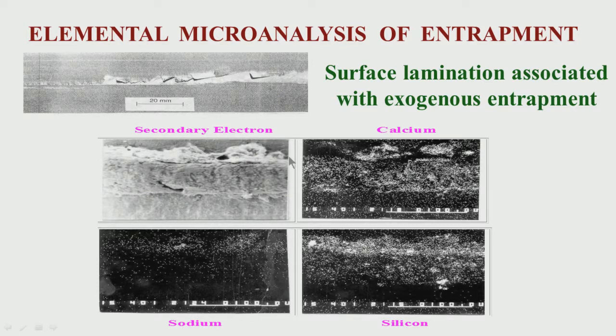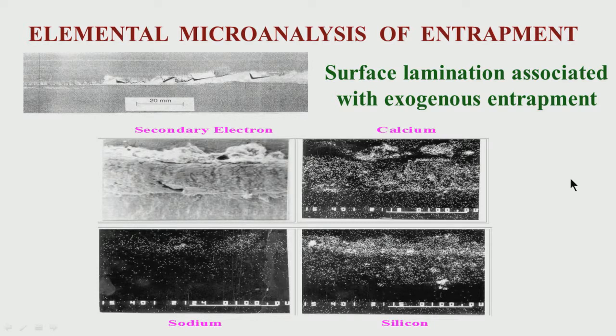From the detector, elemental X-rays are analyzed from wavelength or energy. The defect area showed calcium, lot of silicon, and some sodium. From this analysis we know the source of the defect — since sodium is present, the source is mold slag. We must then investigate why mold slag was entrained: whether there was too much level fluctuation, or whether the mold powder characteristics — its viscosity and interfacial tension — were not suitable. This is an important way of understanding where the defect came from.